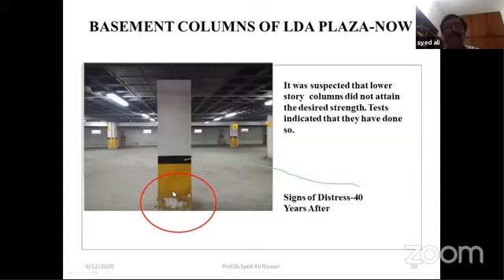can take the cores out, test them, and then you can establish a kind of relationship, a link between the core tests with Schmidt hammer test and pulse velocity tests. So it is a very common technique to establish really what happened. The crack widths on the columns were also noticed, measured with an optical instrument, and recorded. Finally, the conclusion was that the building has almost attained the desired strength.